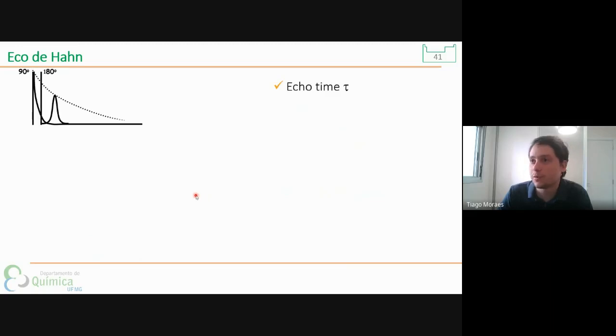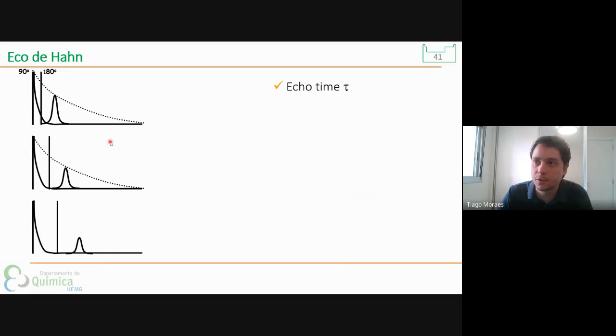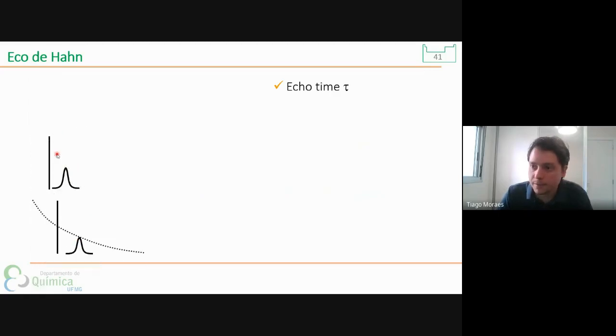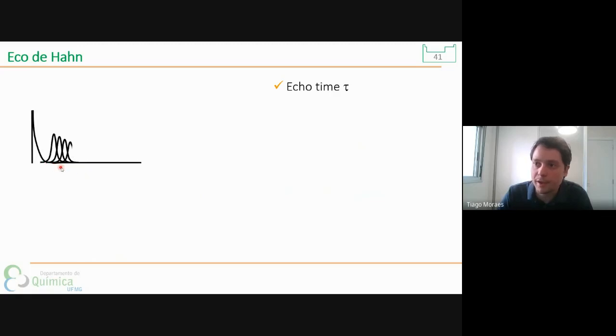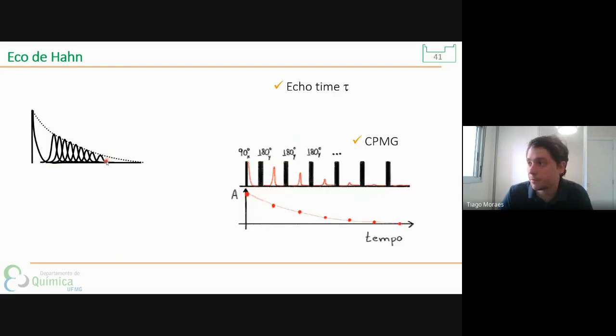Okay, so the idea for the CPMG pulse sequence comes from the spin echo pulse sequence, where you can observe that by changing the tau time, the position of the echo is different. And by doing a lot of echoes with different tau times, you can reproduce the T2 decay, the real T2 decay. That is what we are interested in, right? So the CPMG is a pulse sequence where after each 180 pulse, we produce an echo, another echo here, and the maximum of these echoes produce this decay that is the real T2 decay, right?